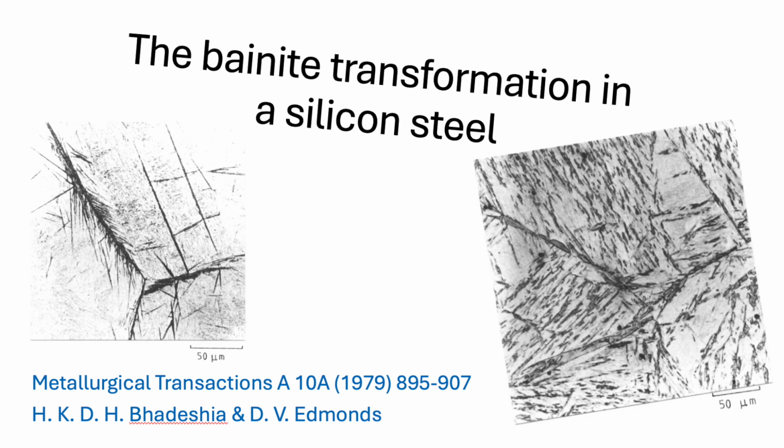So if the carbides aren't forming at the interface via a eutectoid and they're appearing inside the ferrite laths, then they must be precipitating out from the ferrite itself after it forms. And for that to happen, the ferrite must have formed with way more carbon dissolved in it than it should be able to hold at equilibrium. Carbon supersaturation. That's the key fingerprint of a displacive transformation for bainite. The ferrite lattice forms so fast by shear that the carbon atoms don't have time to get out of the way and get trapped inside, exceeding the normal solubility limit.